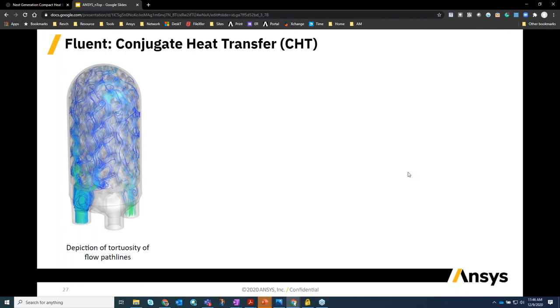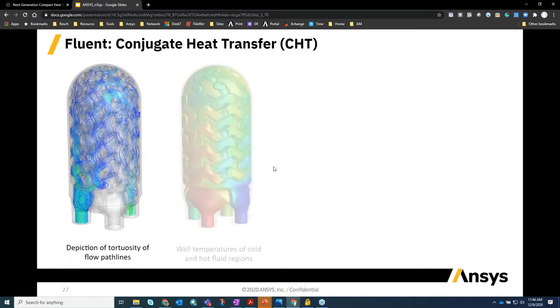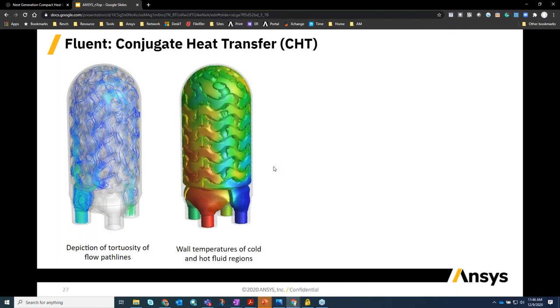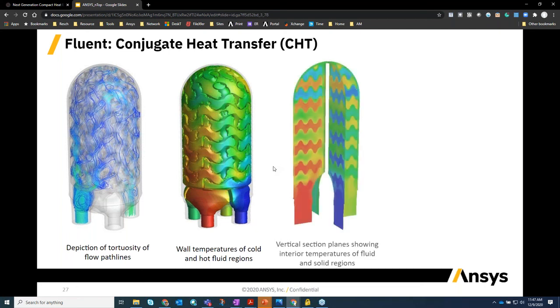And the first thing that jumps out is what Mikey was trying to do, which is to get the fluid to swirl around the entire volume. You're able to see that in the trajectory of the flow. And no surprise that as you look at the temperatures starting from the bottom going up to the top, you're seeing the hot and the cold contours come together, almost converge in a well-coordinated fashion. So I think it's nice how the beauty of the underlying geometric paradigm is showing in these CFD results. And again, another section view of temperatures of the fluid and the solid regions.